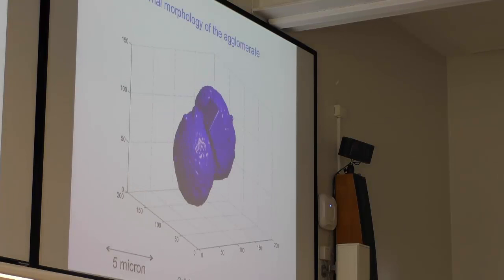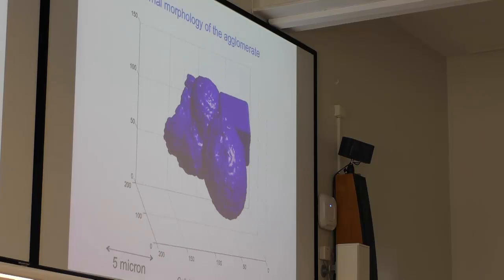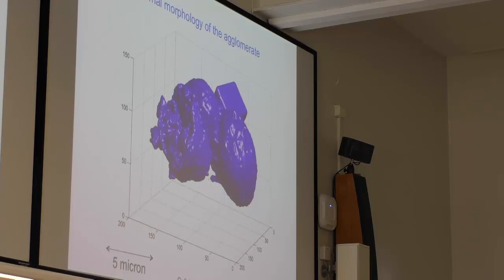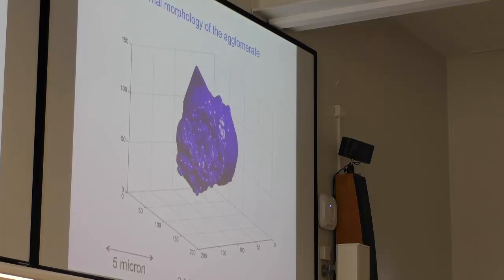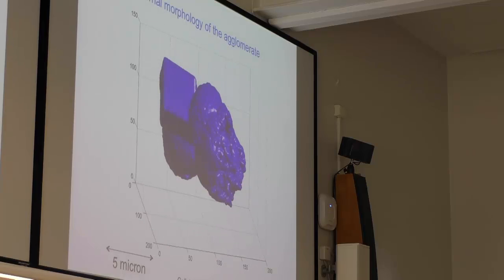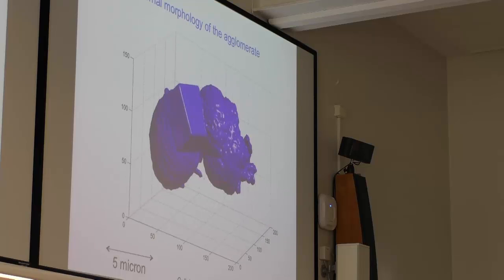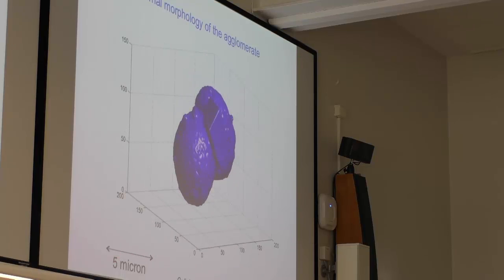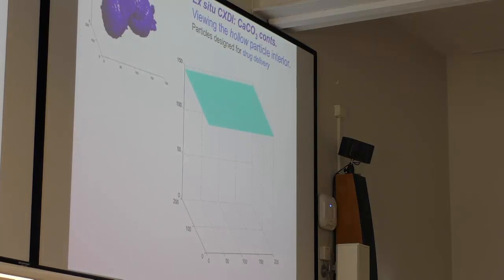And one example is here, where you can see a calcium carbonate, small agglomerated structure, where you can see a calcite small crystallite here. And the scale bar here indicates that we are down at 5 micron, right? And being X-rays, we can clearly also resolve what the particles look like inside. And if you look here, you see that whereas the calcite crystallite here, this polymorph, is dense all the way through, these other agglomerates are in fact porous inside. And again, it's nice to be able to see this non-destructively.